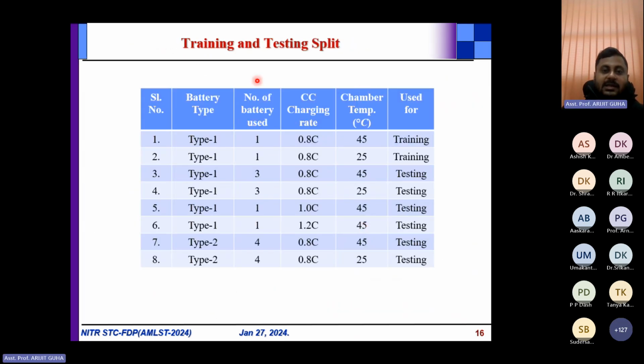Okay, and this is the training and testing phase, in which we have split, as I said, that we have used around 18 cells for testing and training purposes. So at different scenarios, charge times, we have charged the batteries. We have written it here, and we had a thermal chamber where we can cycle the battery at different temperatures. The battery tests were done at two different temperatures. One is at 45 degrees, one is at 25 degrees. I will show you the results corresponding to both temperatures.